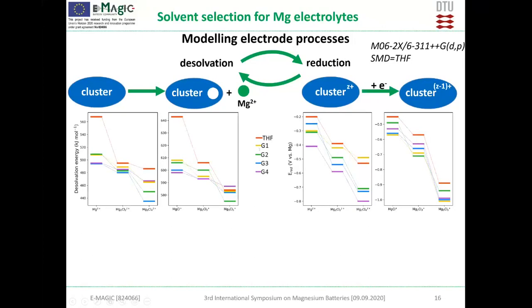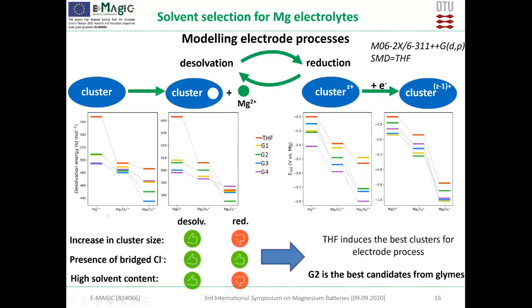And when you compare these results with the clusters that we created, we see that an increase in cluster size has a positive impact on desolvation, because it's easier to remove magnesium when there is also another magnesium in the structure, but it has a bad impact on the reduction. The good impact was found if we have chlorines that are bridging in the structure, so they are connecting 2 magnesiums, because in that case, the electron density shared from chlorine to both magnesiums can be easily shifted from one to another if we remove 1 magnesium or we reduce one of the magnesiums.